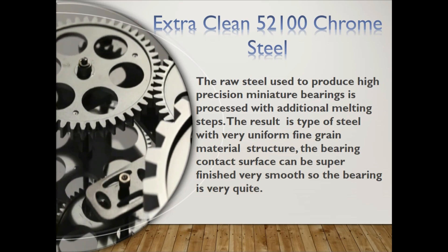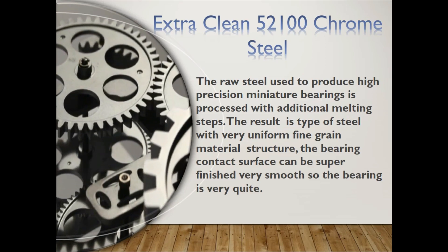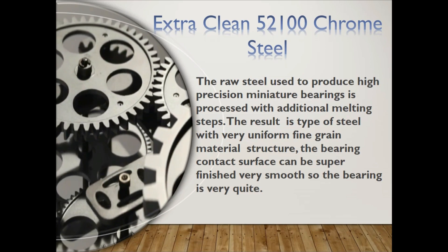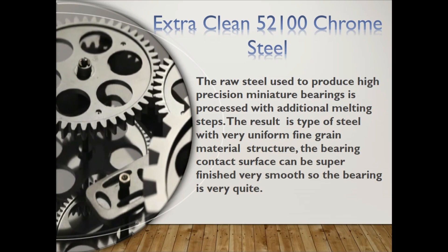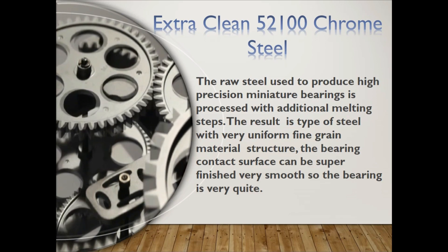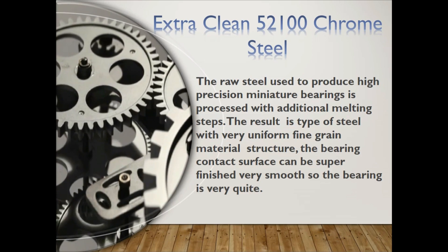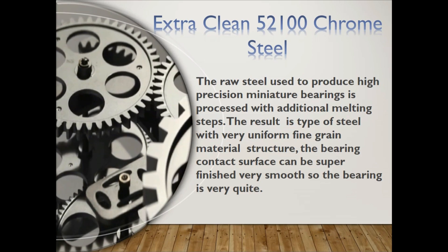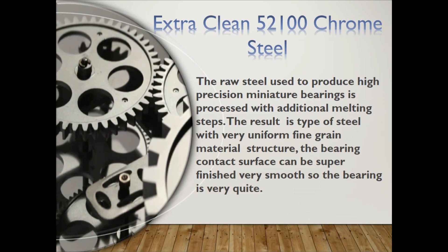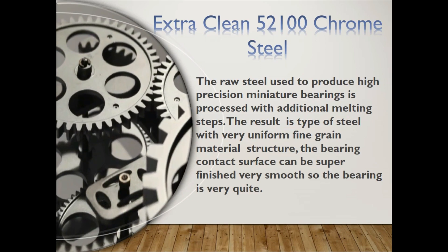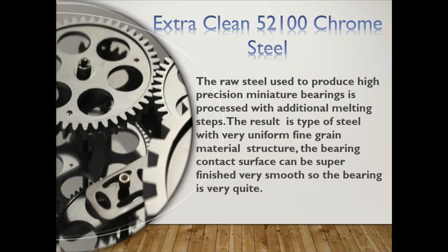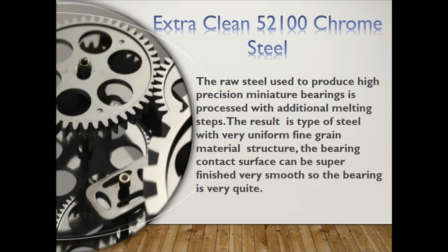SAE 52100 is an excellent general-purpose bearing steel due to its excellent hardness and wear resistance. It exhibits good fatigue life in rolling element bearings. However, the corrosion resistance of chrome steel is poor because of the low chromium content. The surface of the bearing must be protected with a coating of rust inhibitor or oil to stop oxidation.